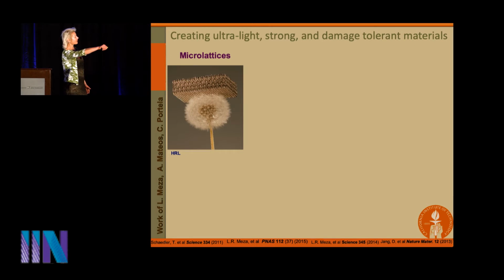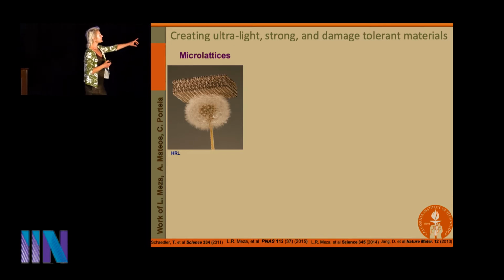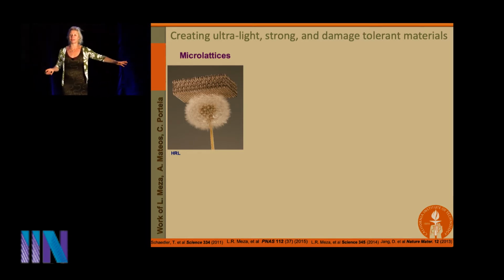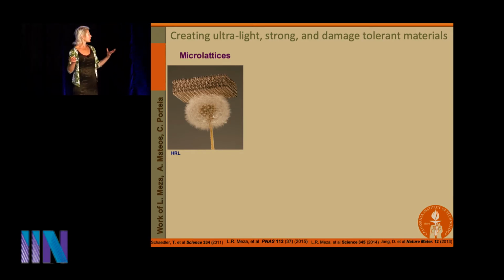What you're looking at here is a microlattice that's made entirely of nickel. This is work in collaboration with HRL, and it's sitting on the world's most normal dandelion. There's nothing photoshopped here. This is not the world's strongest dandelion. It's sitting on top of the world's most normal dandelion and hardly perturbing it at all. So it's exceptionally lightweight. In fact, if I were to hold one of these in one hand and a feather in the other, and then release them at the same time, the feather would fall down faster. These are very, very lightweight.